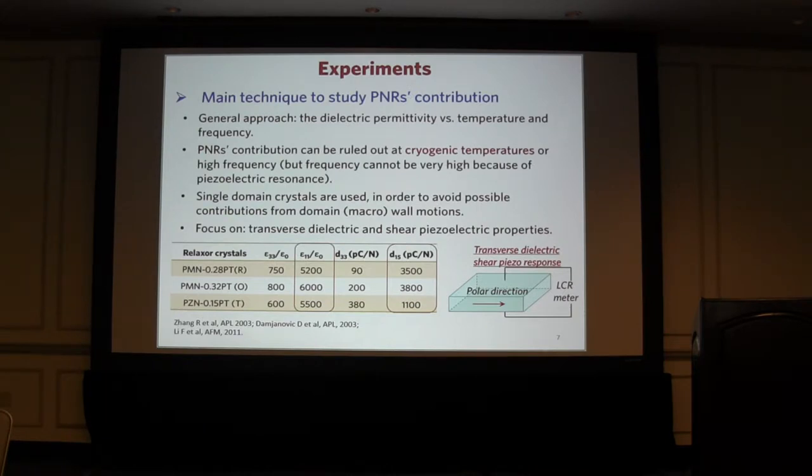We choose single domain crystal for this study because we want to avoid possible contribution from the domain motion. And we focus on the transverse dielectric and the shear piezoelectric properties. You can see from this table, the transverse dielectric permittivity and the shear piezoelectric coefficient are much higher than their longitudinal counterparts. So this is a critical factor for the high piezoelectricity. So in this study, we choose the transverse dielectric permittivity and the shear piezoelectric coefficient.